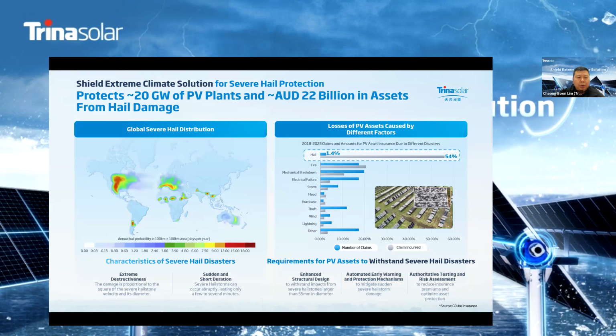So this is the global severe hail distribution, which can happen suddenly and last for a few to several minutes. Then on the right is some interesting data that we have collected from a source, GCube Insurance. You can see that although hail occurrence is one of the lowest among disasters, the damage cost is actually the highest, where we can reach up to 54% of the claims happening on the PV asset.